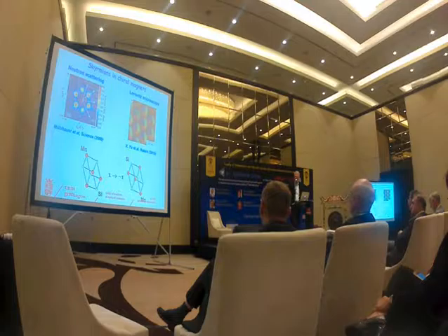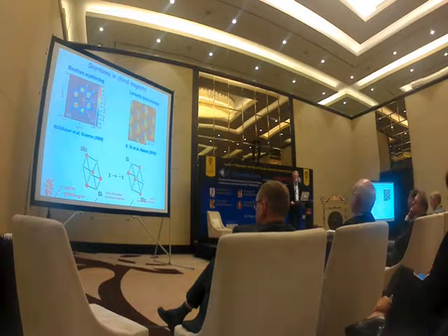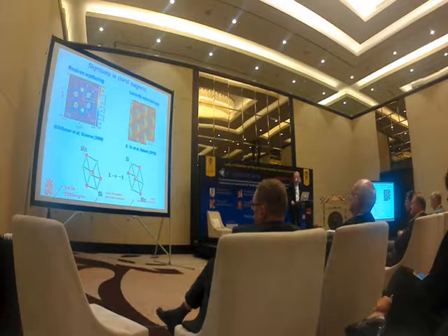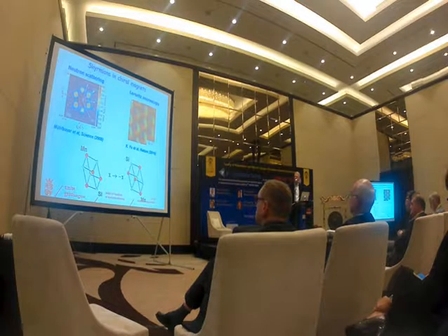One is based on manganese silicide, where silicon has a tetrahedral coordination, and the tetrahedral coordination lacks inversion symmetry, and the manganese is a transition metal that gives rise to the magnetic properties. Here you see examples of these topological excitations by electron microscopy, where you see such a dense network of these so-called skyrmions inside the material of manganese silicide.